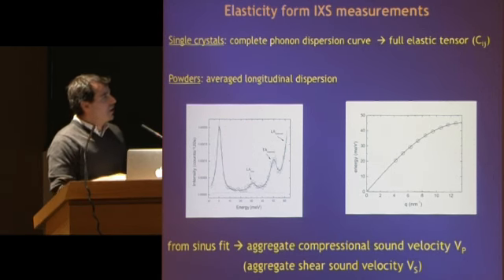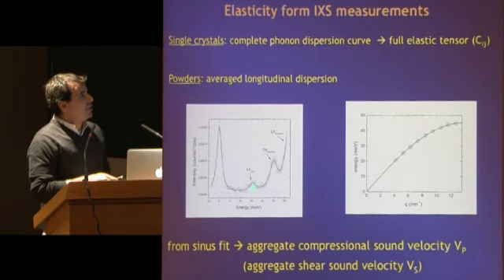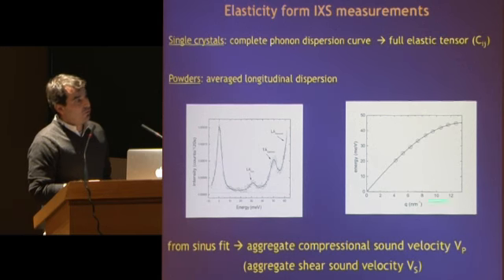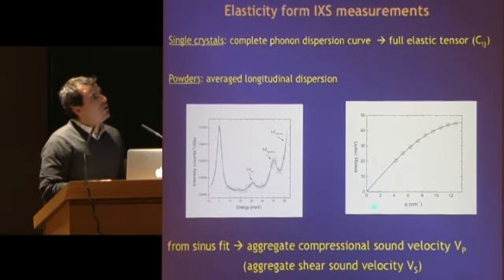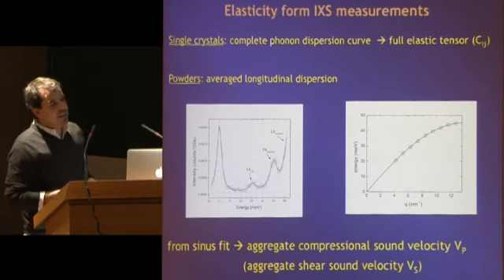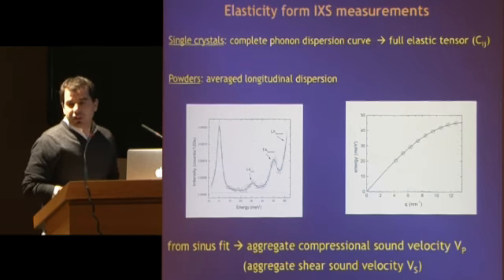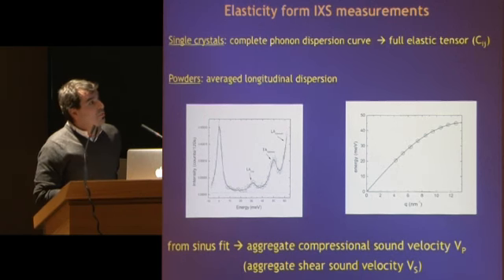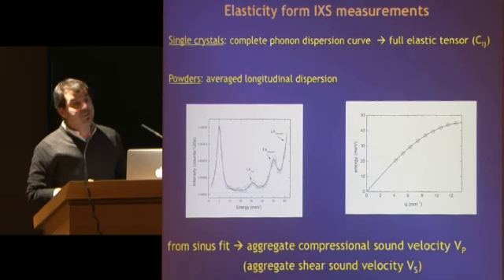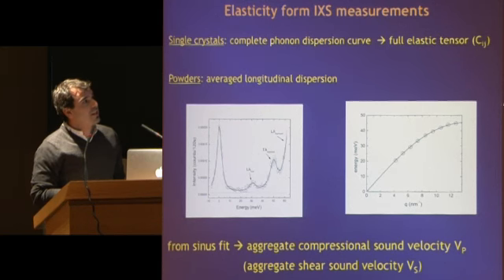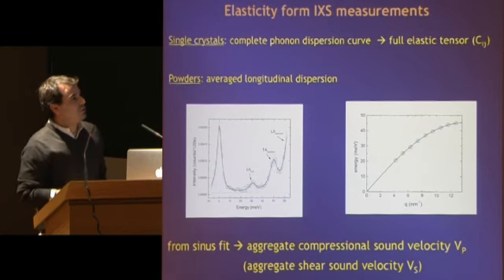So repeating this measurement, determining from the position of this peak as a function of the angle, or if you want, the exchange momentum Q, what we get is the aggregate phonon dispersion that, within a Born-von Karman approximation, if you just consider first-order interaction, can be well described by a sine fit, and the compressional sound velocity Vp is just the slope of the initial part of the dispersion.